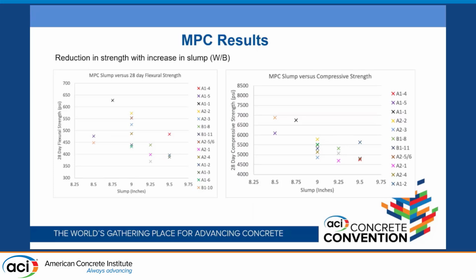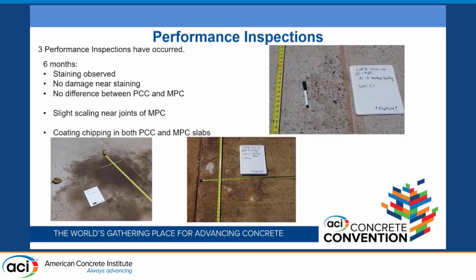So the reduction in strength is with increase in slump. This is kind of the only measure. I didn't have a measure of the water going in. Sort of the only measure I had was the slump, because I know water increases the slump. And in general, you see a decrease in strength with increase in slump coming out of the volumetric mixer.